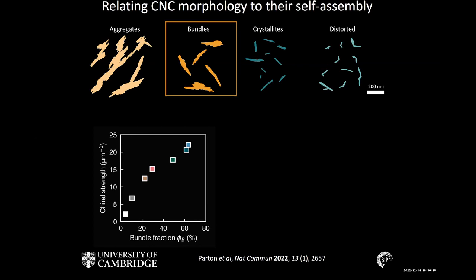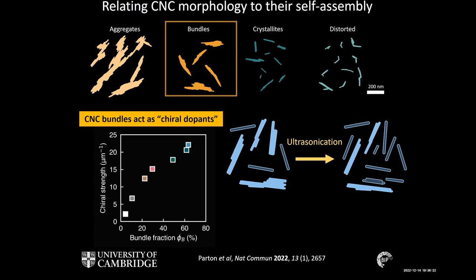And so our particular working hypothesis here for future work is that these bundles effectively act as what are known as chiral dopants. So this is a technical term that's used for liquid crystals, for example in liquid crystal displays. So in a standard liquid crystal, you have an elongated molecule which forms a nematic liquid crystal, which is an aligned phase without any twist. And then you can add a certain chiral molecule, a molecule with either a D or L enantiomer, and depending on which one you add, you can make the whole nematic phase twist in a left-handed or right-handed fashion.